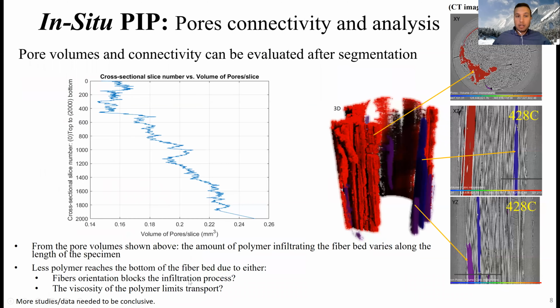The other thing that we can look at is that pore volumes and connectivity can be evaluated after segmentation. And as you can see here, the pores can be separated by whether they were connected. You can see 3 big volumes of pores here. The red, the blue, and the purple are not connected, but they are big volumes of pores on their own.